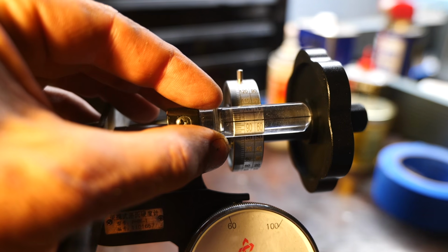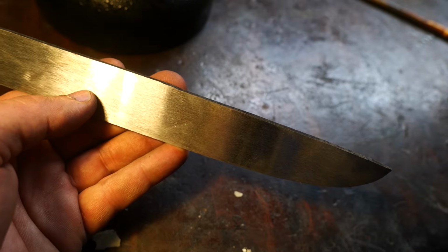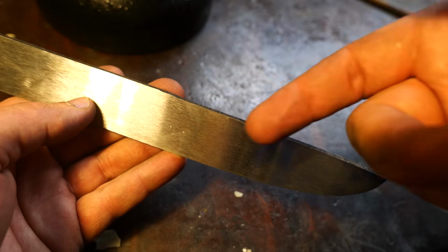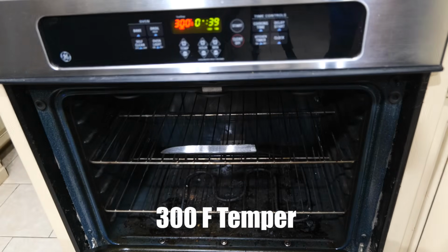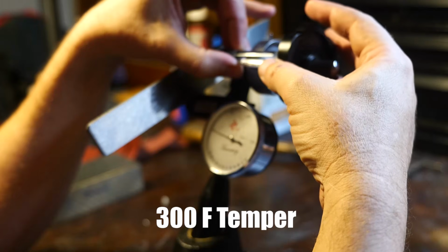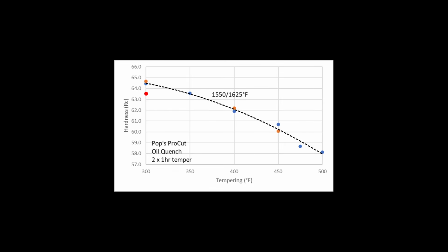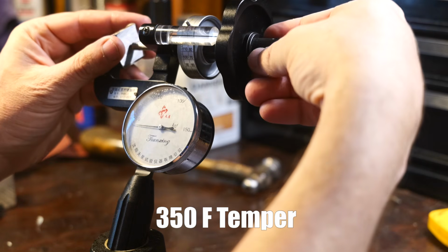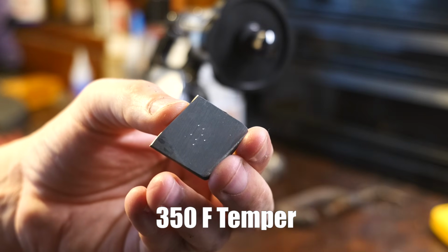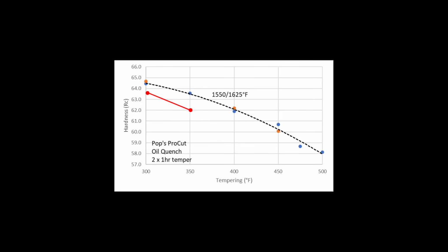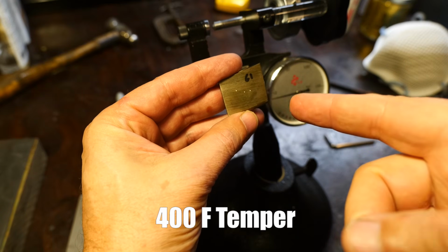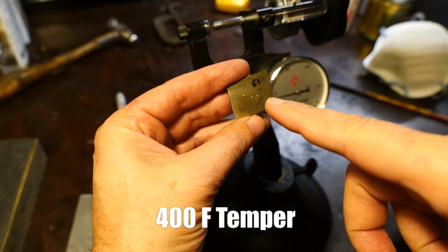This is dead on 65. I don't know if you can see that or not. So 65, 65, and a 66. These were all 62. After 400 degrees temper, I got these 3 readings all at 61.